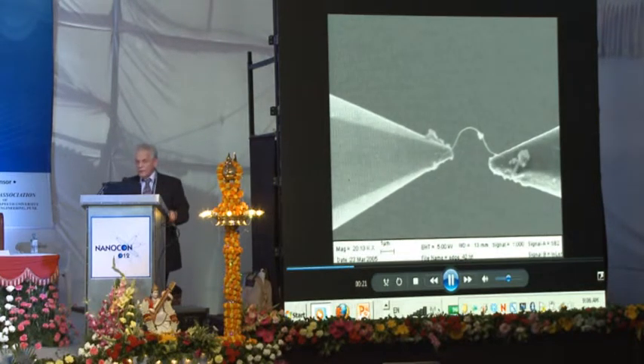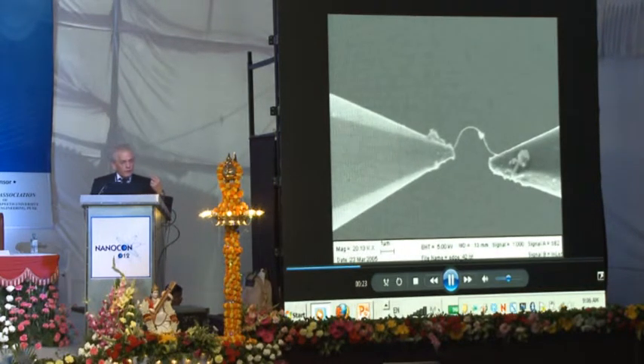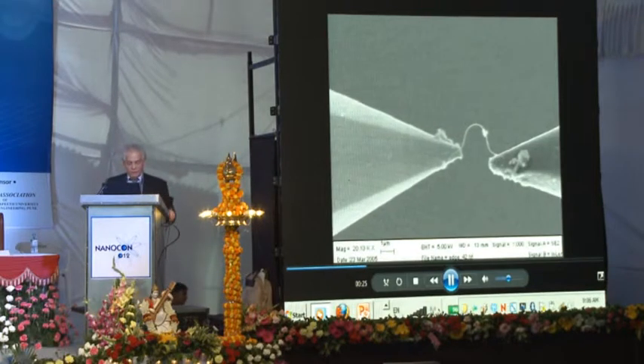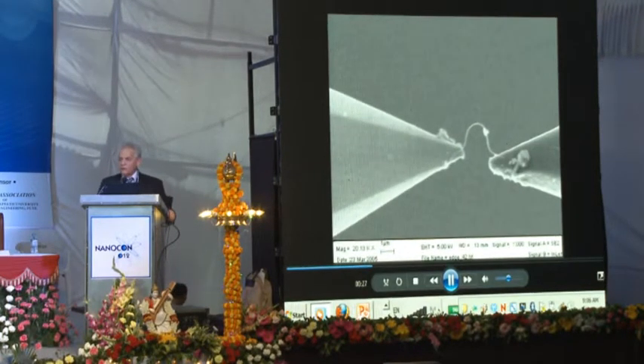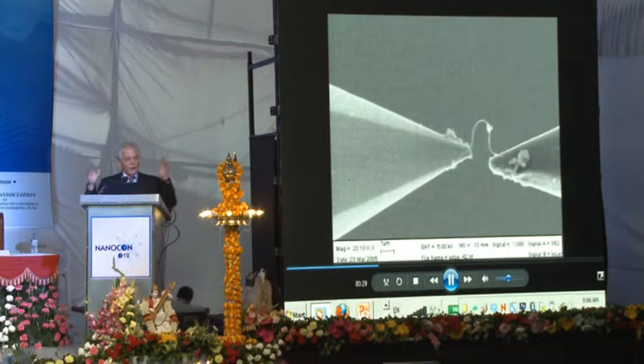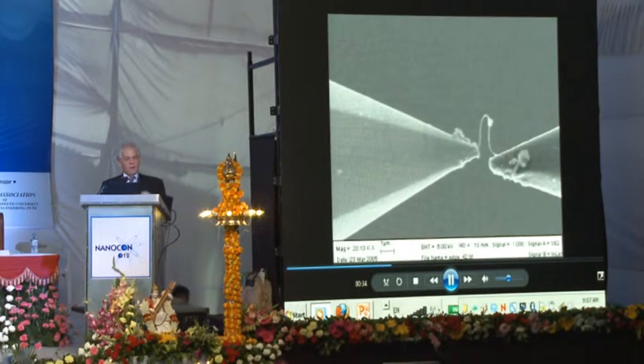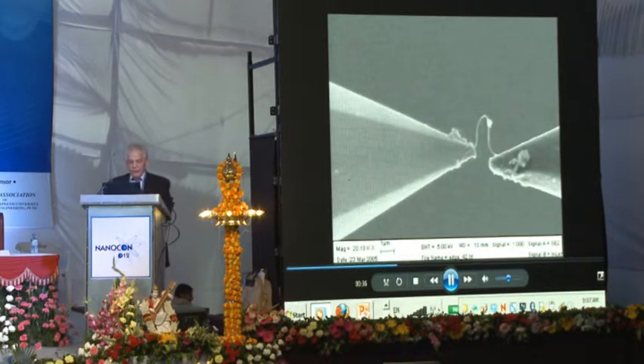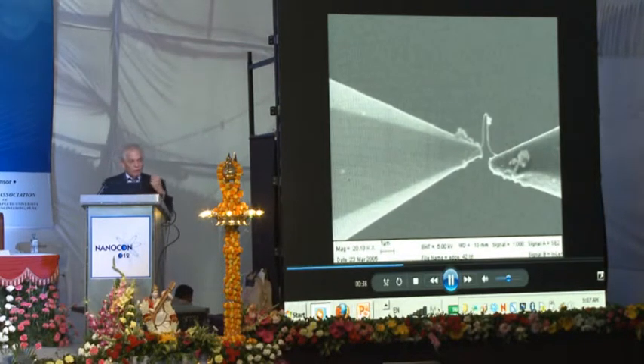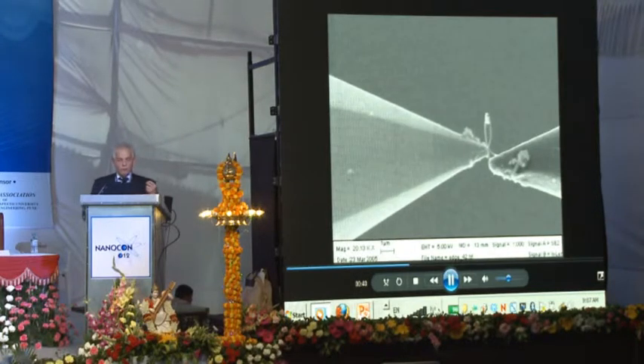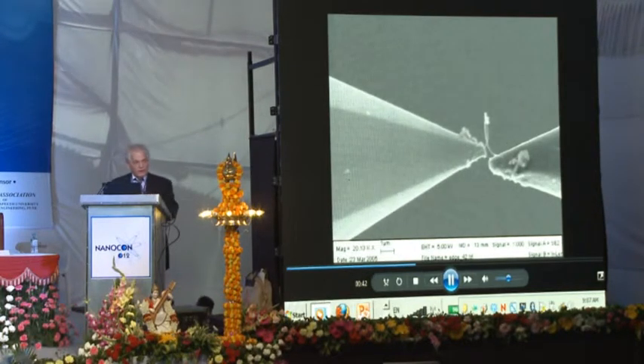So although the nanotubes are, theoretically, not as strong as carbon nanotubes, if you take 1 kilogram of this nanotube, at least 50% of them, or maybe more, will behave the same way. Namely, they will not break even if you push them at 20 gigapascal force.